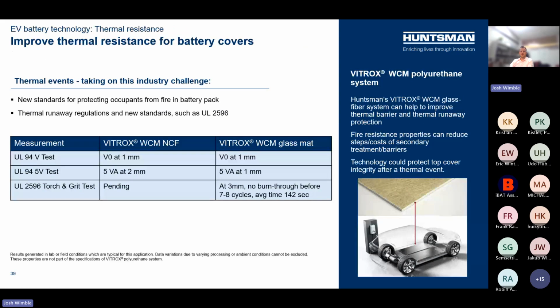What's really exciting to me about these technologies is how they can be leveraged in a single layer glass fiber or non-crimp fabric composite for battery lids. So we have what we call our Vitrox wet compression molded polyurethane system that's designed to meet outstanding flame performance requirements. As you can see in this table here, as thin as 1 millimeter with the glass mat can achieve UL94 V0 and 5VA.